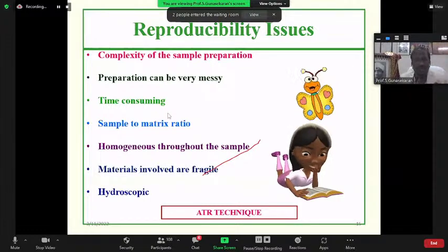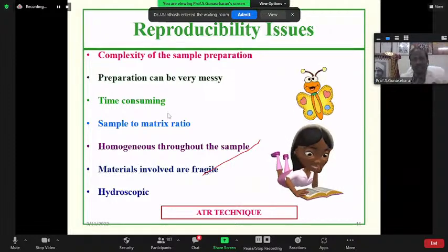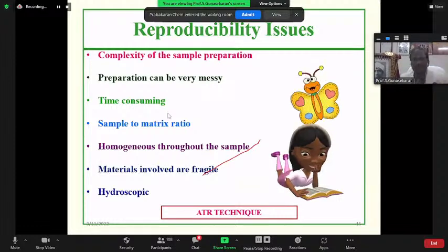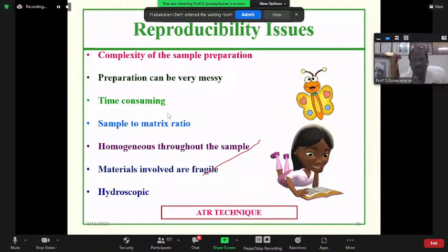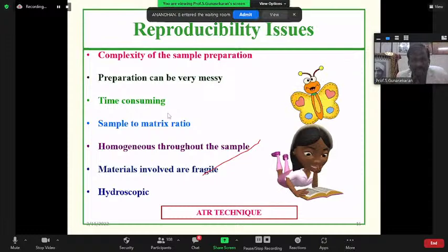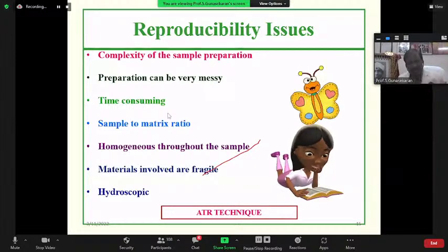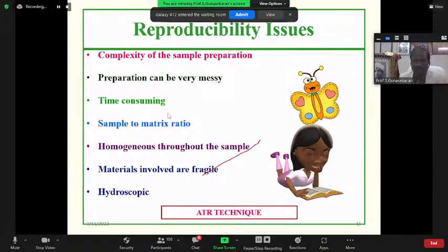I could not expect the sample to matrix ratio to be equal throughout, because for getting a 13 millimeter diameter disc with 1 millimeter thickness of the KBr pellet in this small area, we could not expect the sample to matrix ratio to be equal, because homogeneity throughout the sample is not possible. For quantitative analysis, there should be homogeneity throughout the sample. Otherwise, we could not get proper quantification. And the very important thing is, the materials involved are fragile. We are spending nearly 25 minutes to get the KBr pellet. Before placing this KBr pellet into the sample compartment, sometimes it will break. Materials involved are fragile, easily breakable. If it is fragile, we have to go for second-time sampling. You have to spend another 25 minutes, a waste of time.